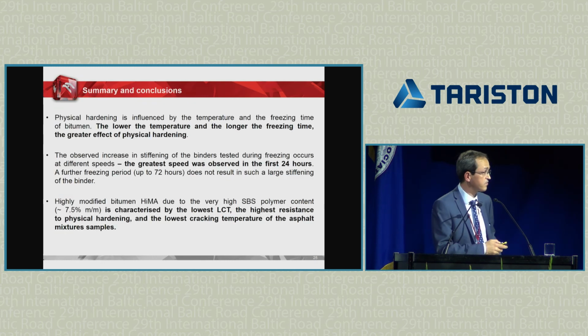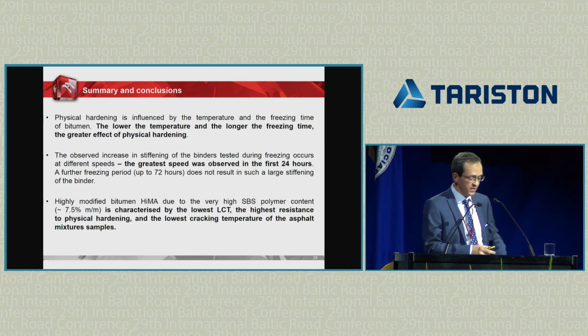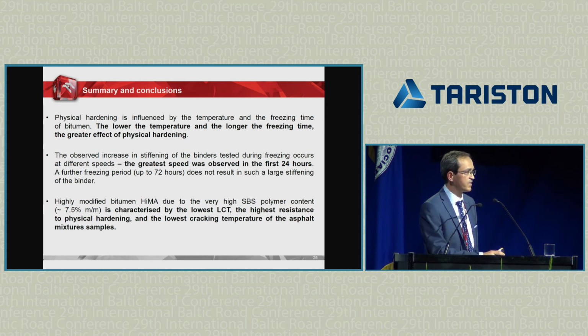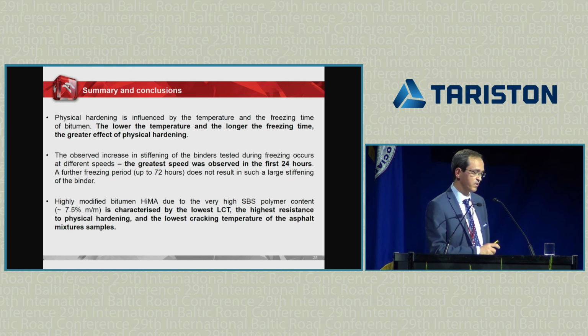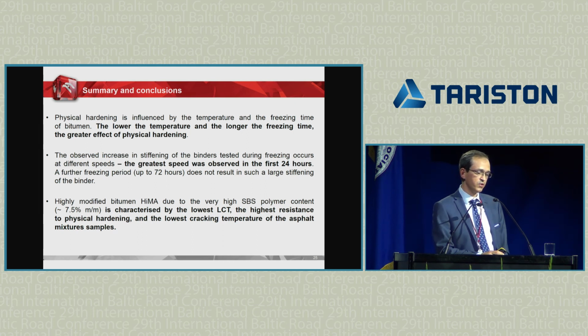And some summary of this presentation. Physical hardening is influenced by the temperature and time of freezing of bitumen. It is obvious that the lower the temperature and the longer the freezing time, the greater the effect of physical hardening. This is also in very good agreement with other publications on this subject. The greatest speed of stiffening is observed in the first 24 hours of freezing. So we could say that the first day at very low temperature is the most dangerous for the wearing course.